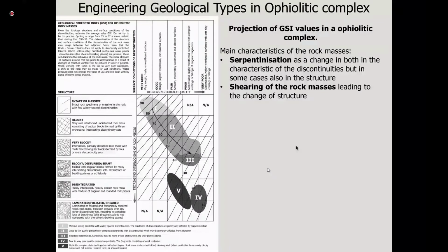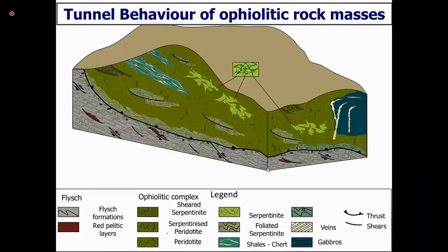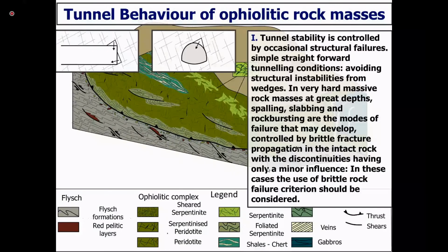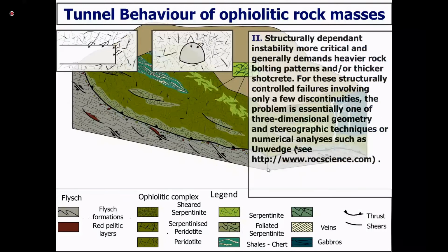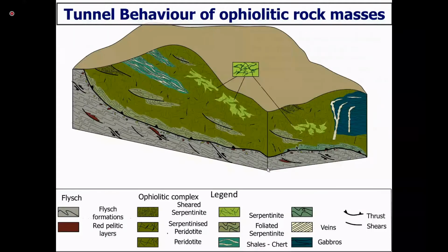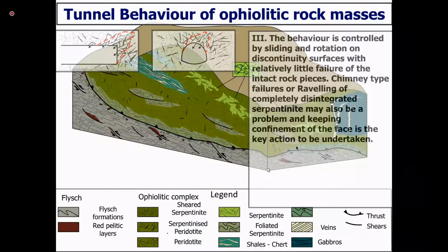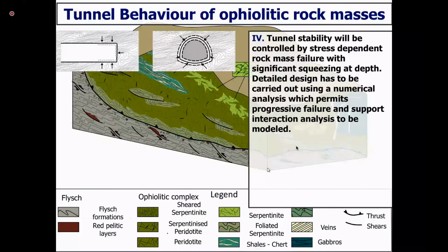So we can shift from quality 1 to quality 2 and 3, and then have the heavily sheared brecciated rock mass due to the serpentinization. And you can understand again structurally controlled failure, or at very large depths, brittle failures. We didn't meet any of these brittle failures in our tunnels. And then crown failures where serpentinization is intense. And when this is heavily sheared and foliated serpentinite, then we have squeezing ground.